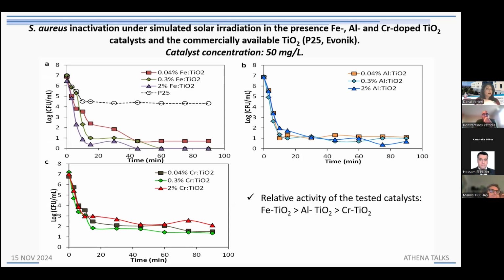the tailing off curve, as I showed you before, regarding the kinetics of disinfection. This verifies the fact that this Staphylococcus aureus, this specific bacterium, is quite resistant. So there is the possibility of remaining cells, remaining resistant bacteria after the treatment. However, we can see an almost 7 or 6 orders of magnitude reduction of our bacterium. Also here another detail, as you may see, we worked with really high initial bacterial concentrations. Those high initial bacterial concentrations are not normally found or detected in environmental samples.